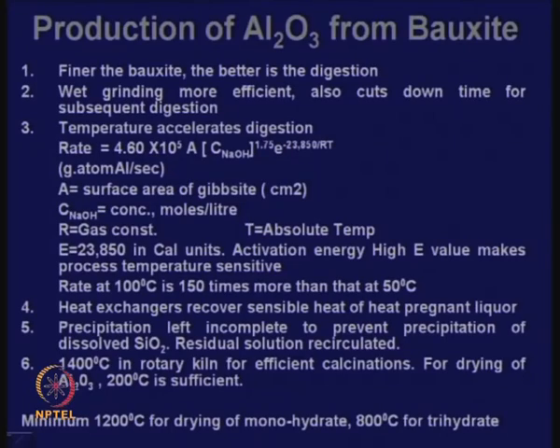When alumina is being dissolved by Bayer's process, it is not very selective. It is not that only alumina will dissolve and nothing else will. Some silica would also definitely dissolve. So, in the solution, you have alumina, and you have small amounts of silica also. Now, one has to be very careful, because if you precipitate alumina, silica would also precipitate. This is where a compromise has to be made between total recovery and quality.